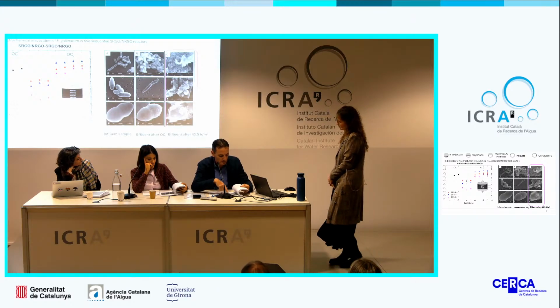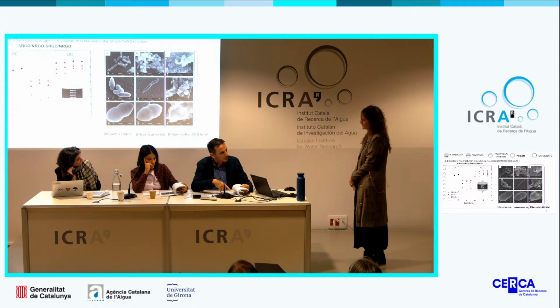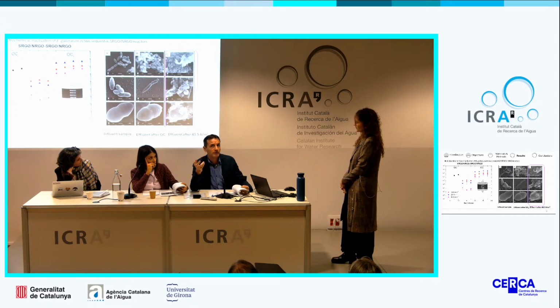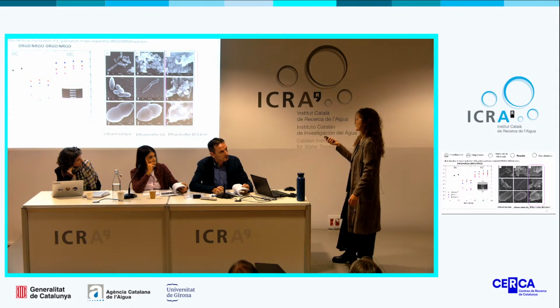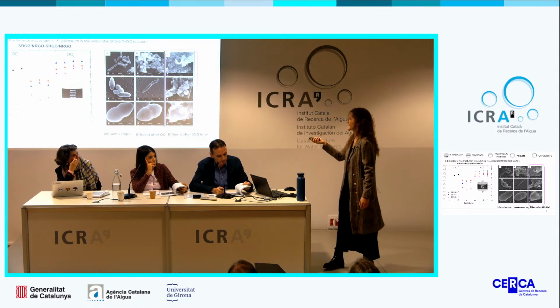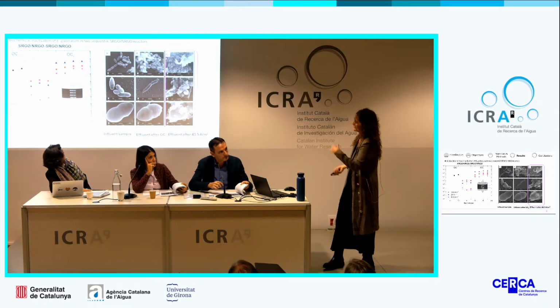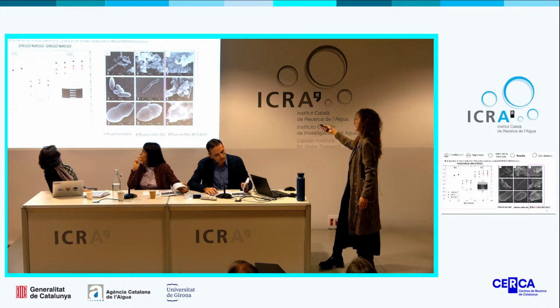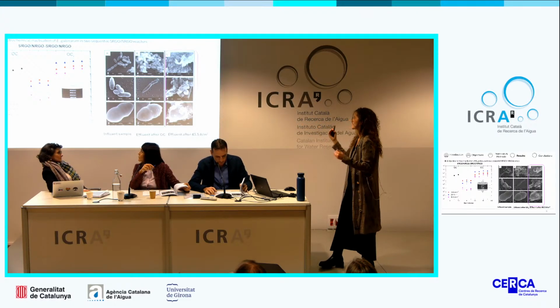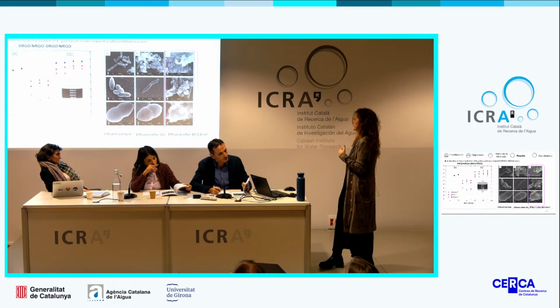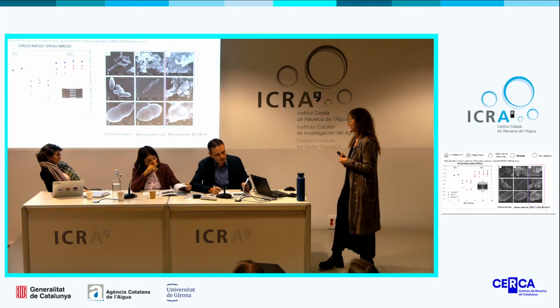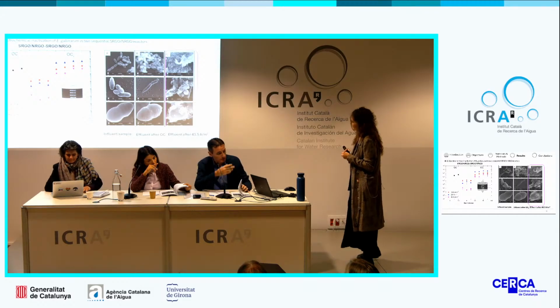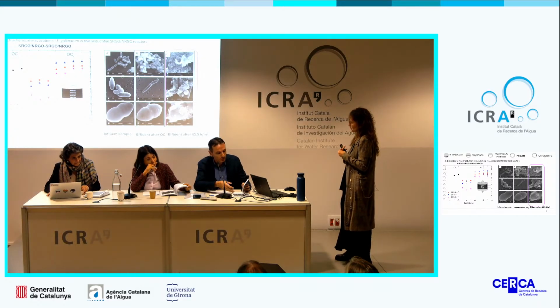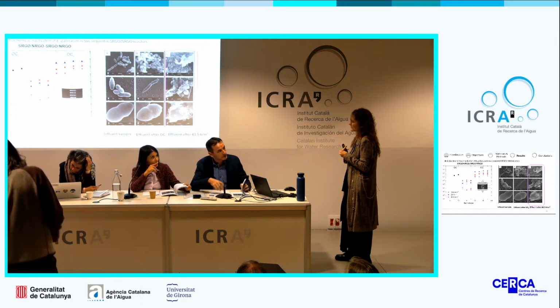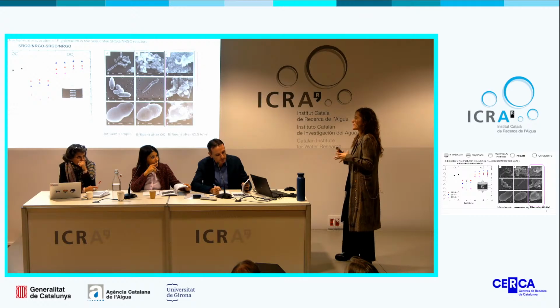Yeah, that's my question. If you have only a micrograph at 43.5 amperes per square meter, or you have a set of conditions, do you know that the mechanism changes depending on the current that you apply? Yes, of course. We can confirm this according to the graph on the left. This is the highest current, but with the medium current, we do not achieve as much removal as with the highest one. So, of course, it's affecting the disinfection treatment. But you don't achieve that removal because you don't produce enough oxidants or because you don't create enough pores on the bacteria? Maybe it is probably something in between.